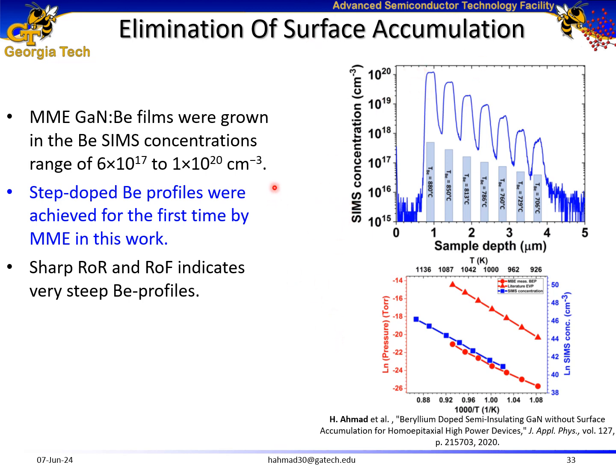So in this regard, I grew beryllium-doped gallium nitride films with beryllium doping levels of 6 times 10 to the power of 17 to 1 times 10 to the power of 20 per centimeter cube. And I achieved beryllium step-doped gallium nitride profiles for the first time. And these profiles show sharp rate of rise and rate of fall.